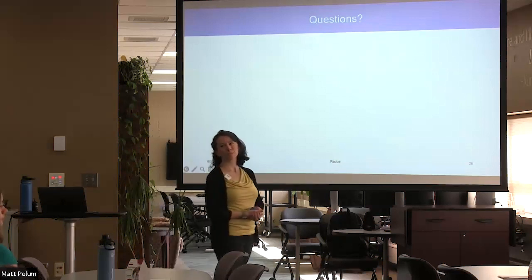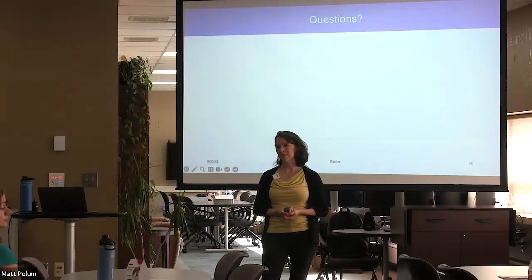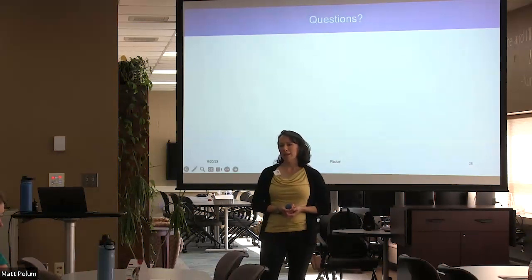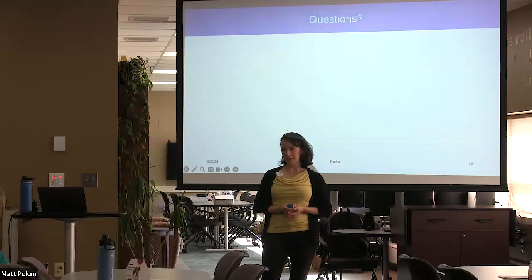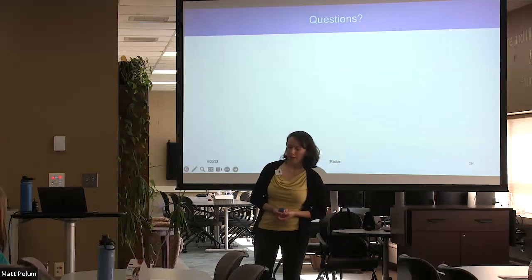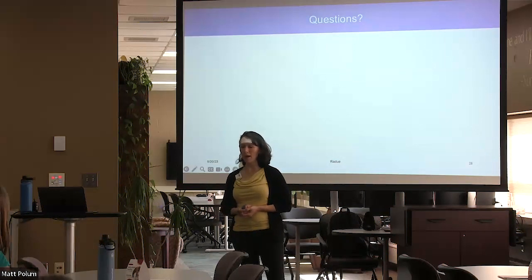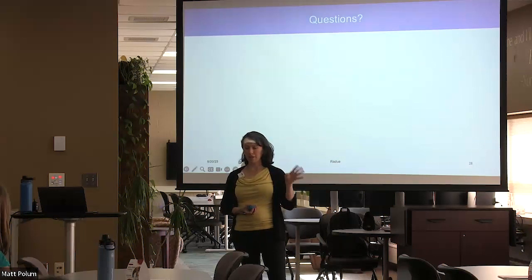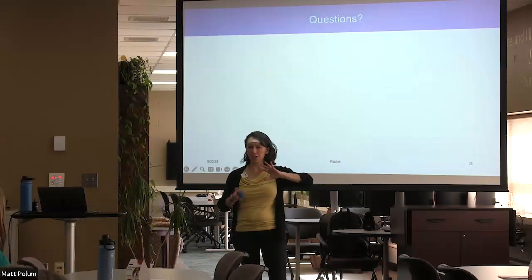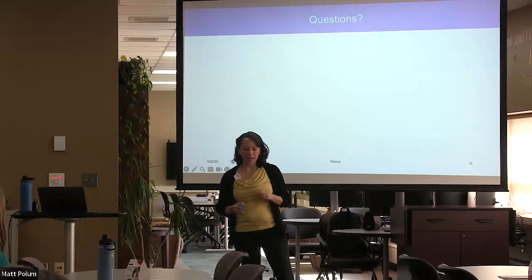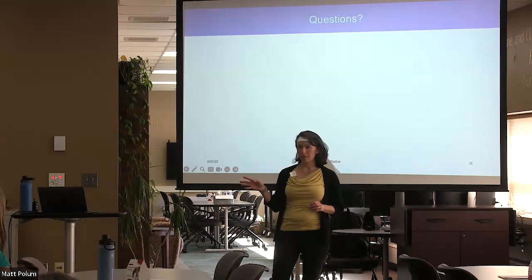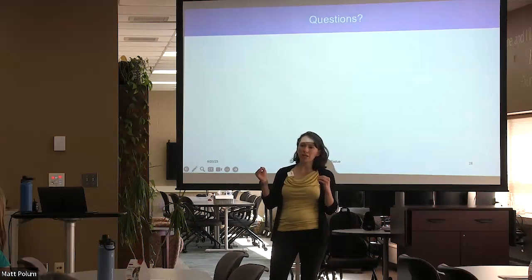So by using all three techniques, which each tell you something a little bit different about that, you would be able to describe. Yeah. So my hope is, and it's a promising start so far, that the FTIR and the Raman spectroscopy can tell us about the phonon modes and the structure, and are there bonds breaking? Are there bonds shifting in energy? And then the surface plasmon resonance can help tell us about what we call the electronic structure, or how free the electrons are to move.